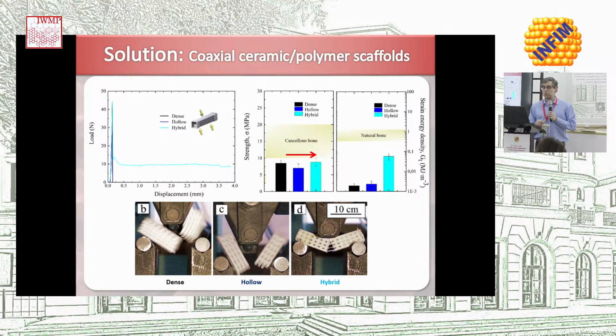And the amount of strengthening that we observe, well, no strengthening, sorry, as expected, because basically we have the polymer on the inside, and in bending, the material is breaking from the outside, so polymer is not doing anything there, so strength remains the same, but we do get a very substantial improvement in the toughening. And we have a more than 1 order of magnitude improvement in the toughness and the strain energy density, which is basically a measurement of toughness in the material. So that's what we wanted. This is a very good solution for that.